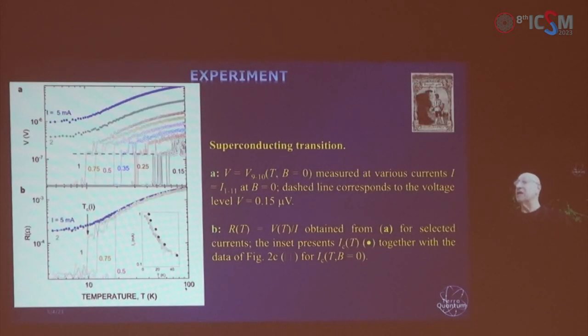Another remarkable observation we make is that there exists a metastable state at half voltage or half normal resistance, as we see in the next slide. There is a metastable state which appears at different times. And then we can see that indeed this resistance follows the expected Josephson junction correlations and the expected dependence on the temperature.